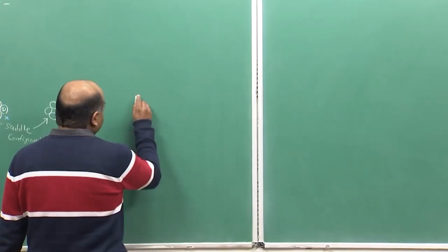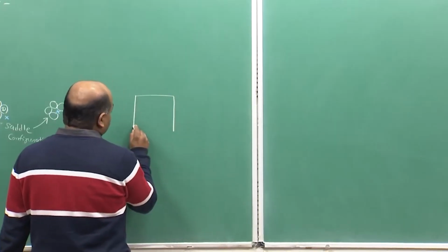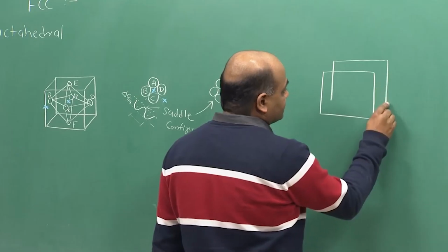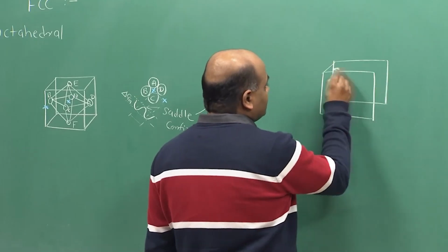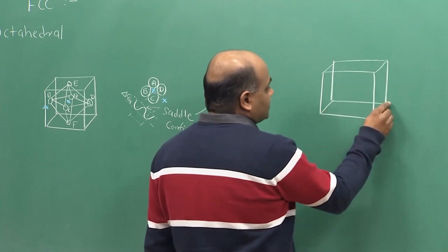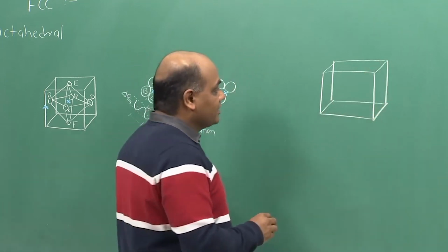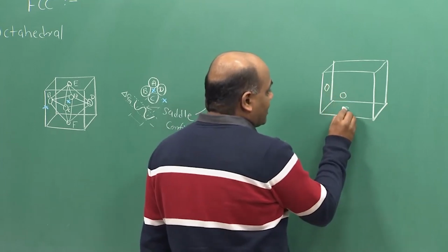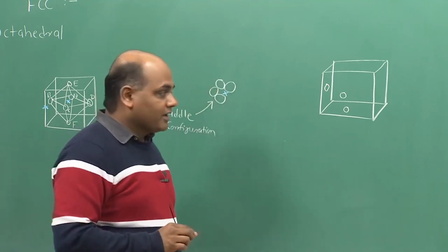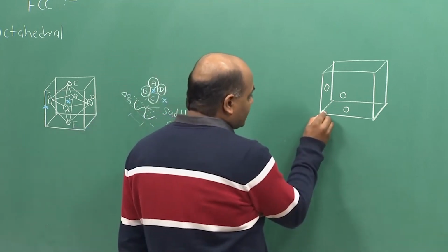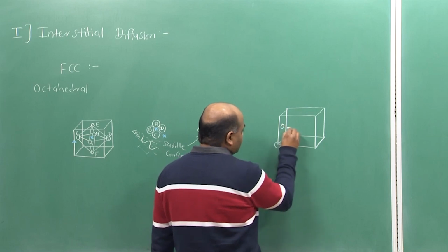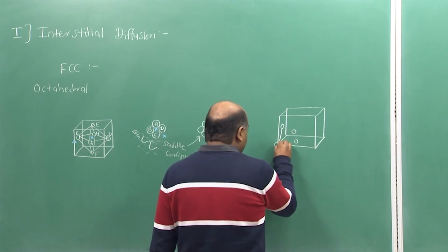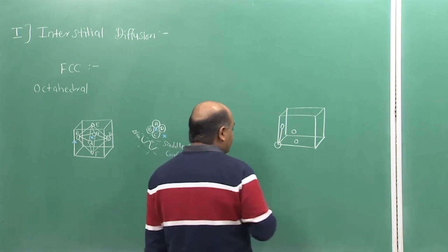Similarly, there will be tetrahedral interstitial sites in FCC, those lie along the body diagonals. So, if we consider any three adjacent face center atoms, and the corner atom which all the 3 face center atoms touch, then we can draw a tetrahedron, meaning a figure having 4 faces.